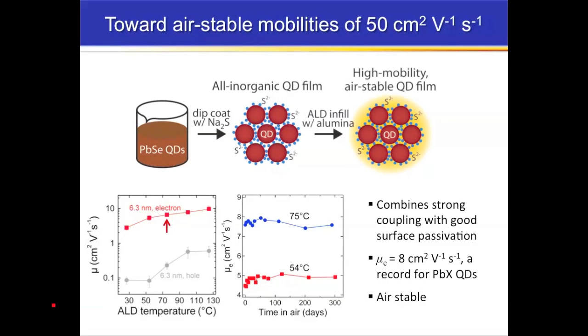Let me show you a final way that we've been able to improve the mobility almost to 10 centimeters squared per volt second. This is by using, instead of organic ligands, very small inorganic ligands to couple the dots. So we take a solution of quantum dots, we do a ligand exchange, in this case with sodium sulfide, and so each of these little blue spheres here is a sulfide ion. And then we do the alumina infilling using a low temperature ALD process.